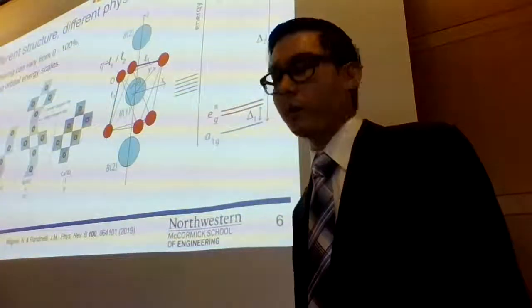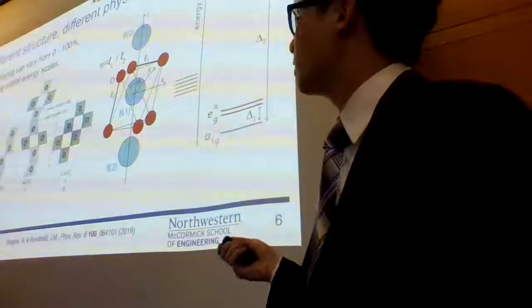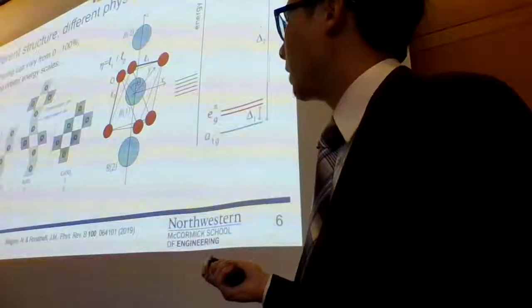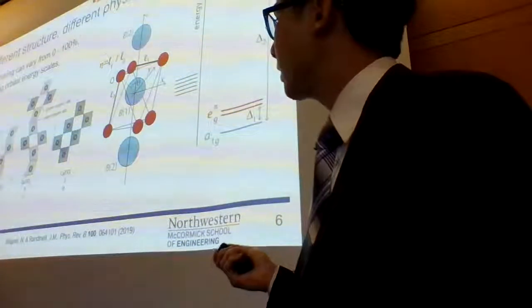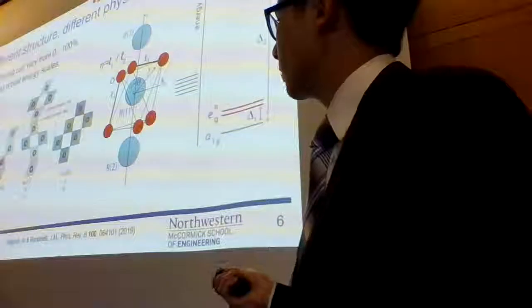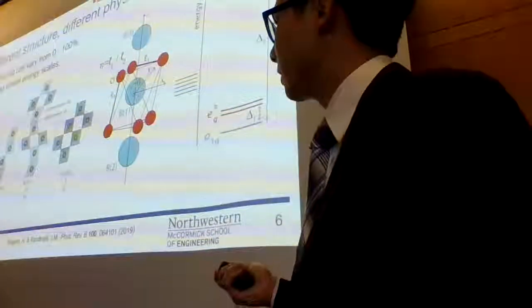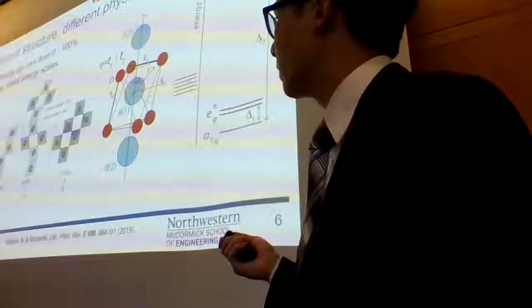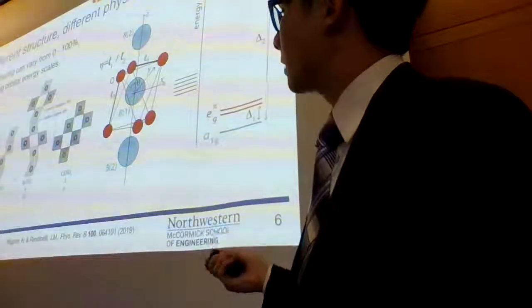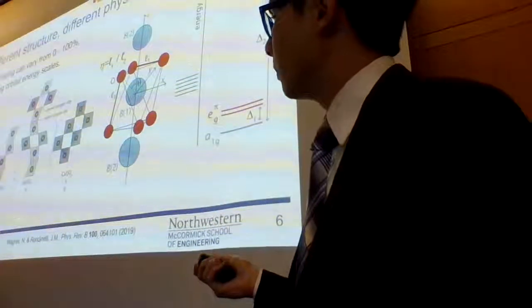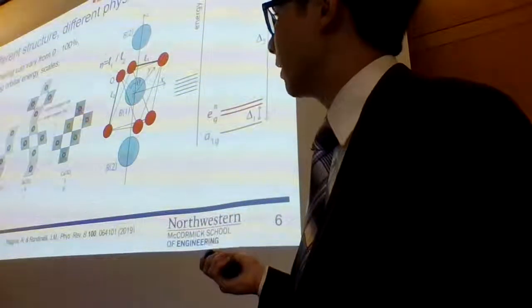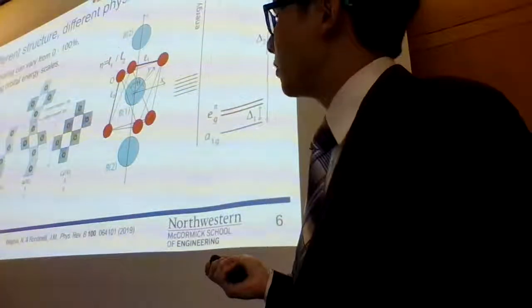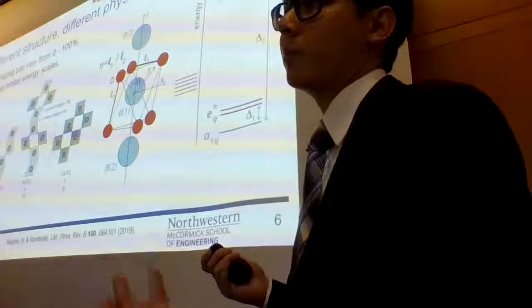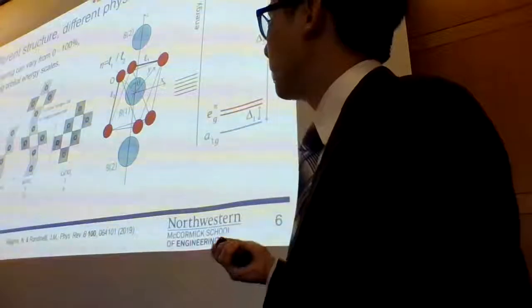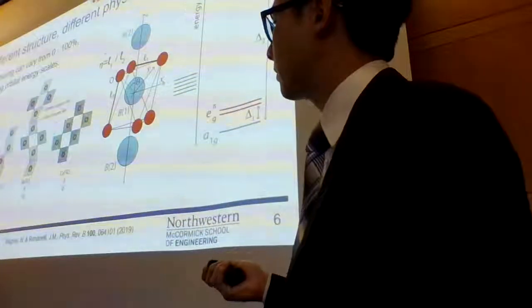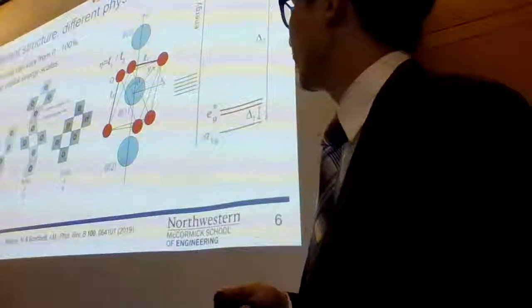So one thing that's unique about these structures is that you can have gradients of the amount of face sharing. In the prototypical cubic perovskite example, you have only corner sharing between the octahedra. Whereas you can have the end member with full face sharing, but you can also have gradations that you can think of as a knob for tuning properties potentially, depending on the structure here. Intermediates of say 50% face sharing or 33% face sharing.